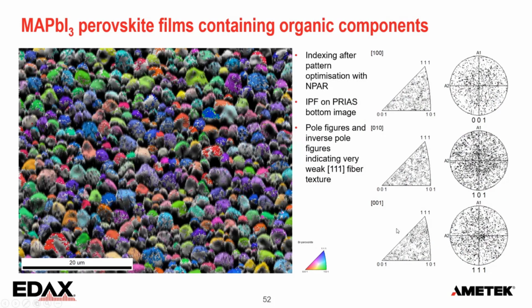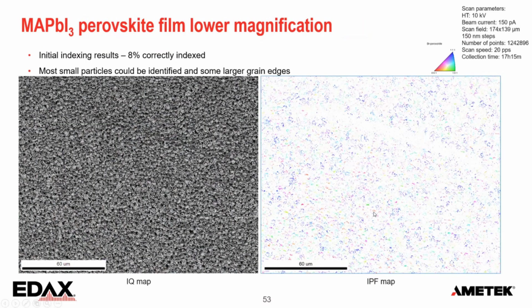Now, based on that, we remove all the bad points, as I've done here. And there's the texture. So with a bit of imagination, you can say, okay, there seems to be a little bit of a peak here in 111, but it's extremely weak. It's almost random. Now, then I tried the same trick on a larger area.